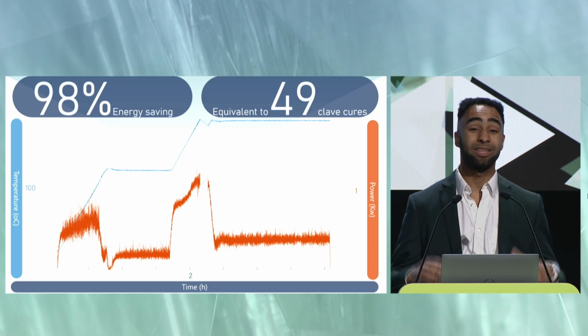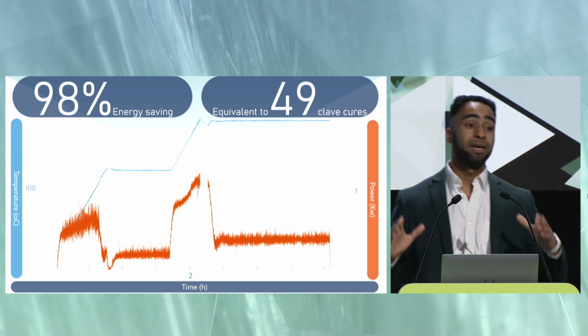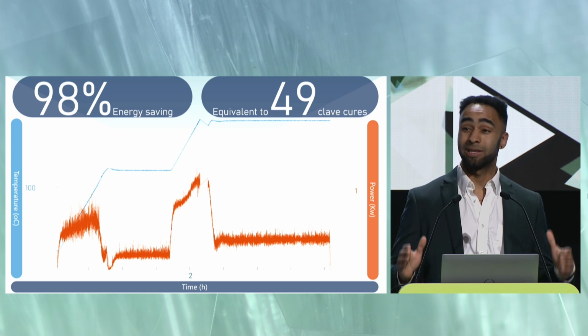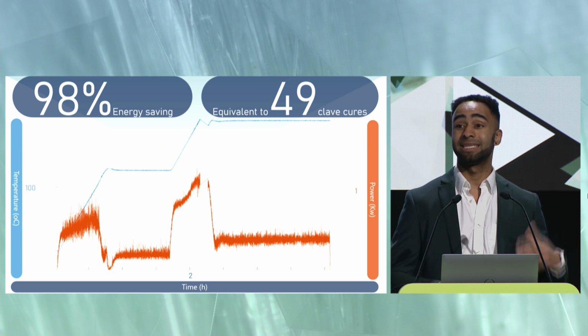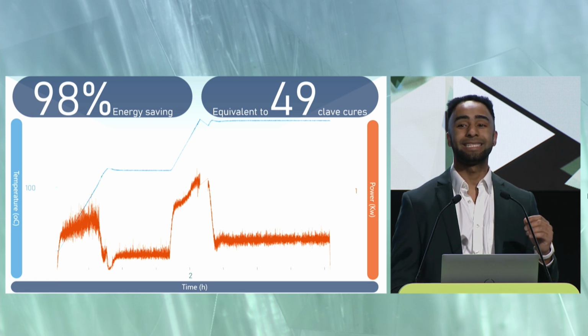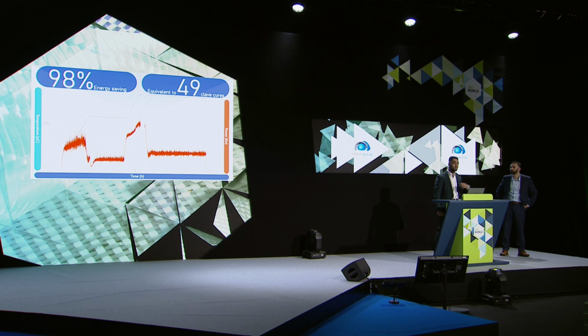So this is the real reason why we put this project together. Curing that tool off, that 4-meter long wing skin tool, using the embedded EcoTool heaters, uses 98% less energy than curing it in the autoclave. When we come to components, we're using a peak power of 1 kilowatt, which is the same as your microwave. It's absolutely ridiculous, the difference in energy between the autoclave and the EcoTool system.